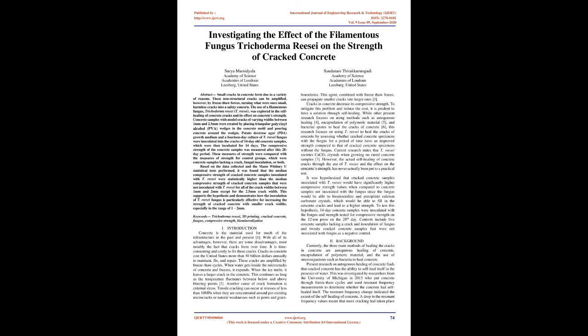Since these p-values were all less than the significance level of 0.05, there is statistically significant evidence to conclude that there is in fact a difference between the median compressive strengths of cracked concrete samples inoculated with fungus and the median compressive strength of cracked concrete samples not inoculated with fungus for the 1 mm, 1.5 mm, and 2 mm crack widths.